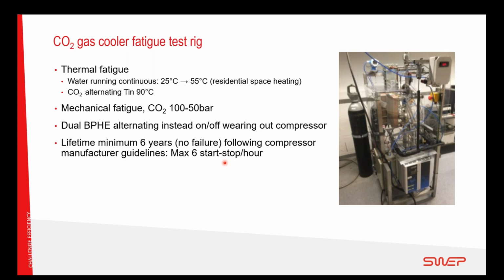water, and about 9 case in the test being pulsated from between 100 to 50 bars. And in this test rig, we build it with dual heat exchangers, so we are alternating between the heat exchangers instead of wearing the compressor out. And then we have the cooling water running continuously and the compressor feeding the heat exchanger with carbon dioxide, and that one is alternating. Under these conditions we did about 350,000 cycles without creating a failure at this point.